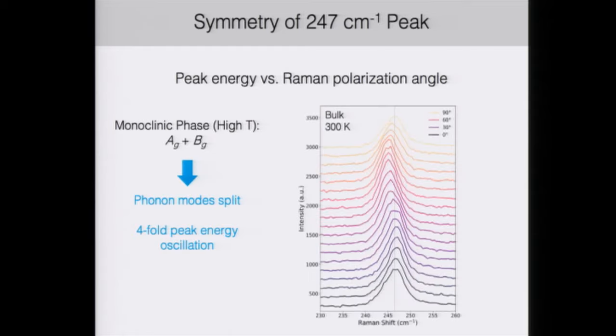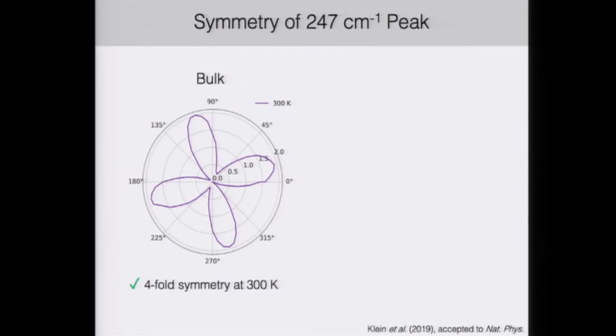And so we can see this in our raw traces here in bulk sample at 300 Kelvin. And so we can look at the peak energy shift as a function of polarization angle. And so in bulk at 300 Kelvin, we see this 4-fold pattern consistent with what we expect for a monoclinic symmetry. As we cool down below the phase transition, we see that this symmetry has nearly vanished.